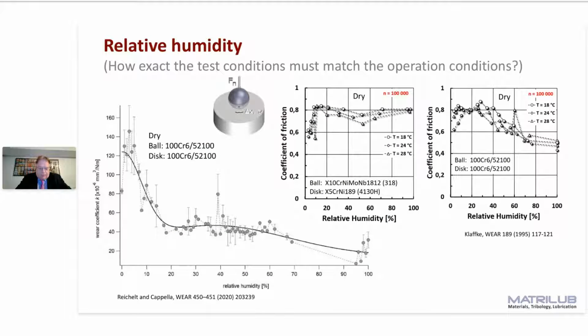Okay. Another important point, especially under dry friction, but even in some cases also under lubricated conditions, is relative humidity. At least under lubricated tests, you should record the humidity. Under dry conditions, you must really control the humidity. You see here in an oscillating test under dry friction with ball bearing steel, you have the wear rate or wear coefficient as a function of the relative humidity. And what you see is that your results can be tailored by the humidity. And depending where you live, depending on the season, you can get different results.